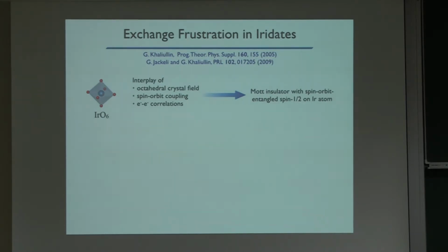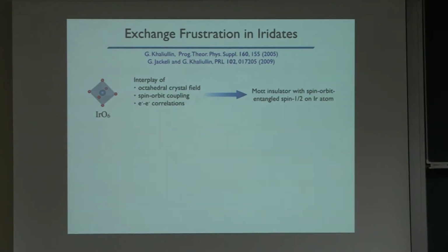And in order to get Kitaev interactions, you need really several different mechanisms to conspire. So what you first need is a very particular microscopic structure. So you want the iridium atom, that's the magnetic site, you want it to be surrounded by 6 oxygens that form this octahedral structure. And this octahedral field will split the degenerate orbitals for the iridium atom. Iridium is quite heavy, so you have a large spin-orbit coupling, which further splits the orbitals. And it splits them so far apart that even moderate electron-electron correlations can drive you into Mott insulator phase.